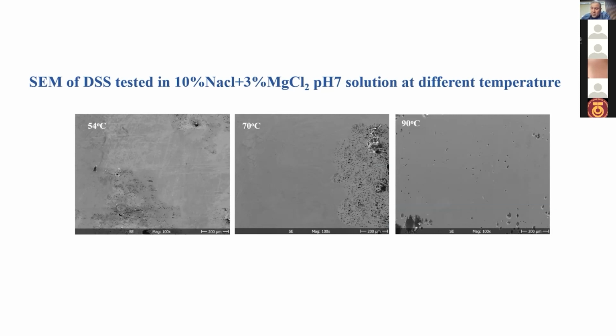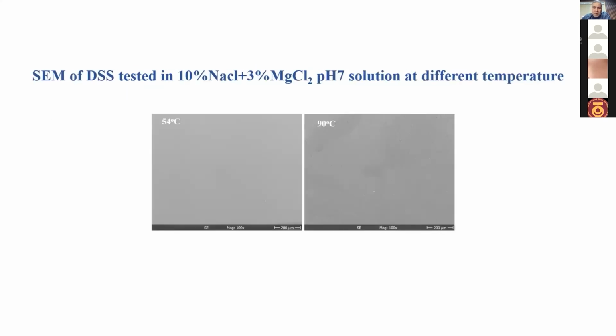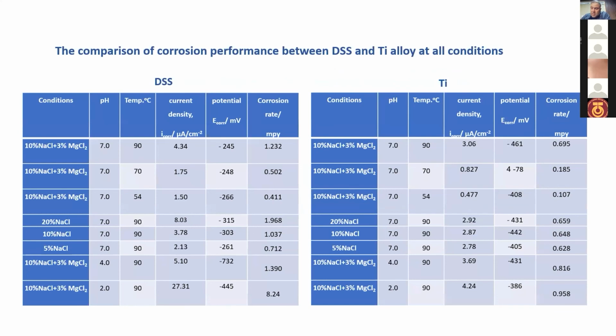Finally, for these two alloys, now we go to these two tables. They summarize the results obtained in the electrochemical corrosion tests under the different conditions, and prove that titanium has superiority over duplex stainless steel in resisting corrosion and pitting. This is due to several factors, the most important of which are the elements that make up the alloy, such as tantalum, molybdenum, and aluminum, which make the oxide film more stable.